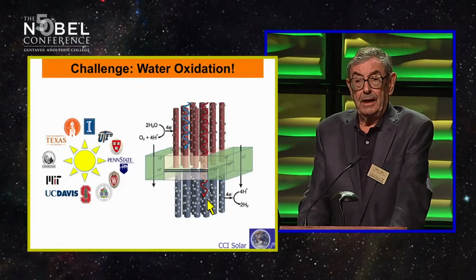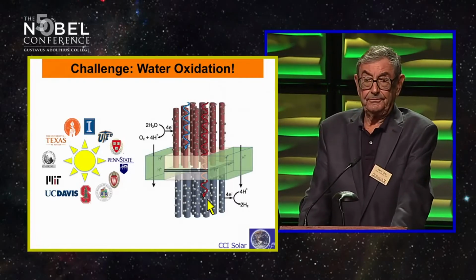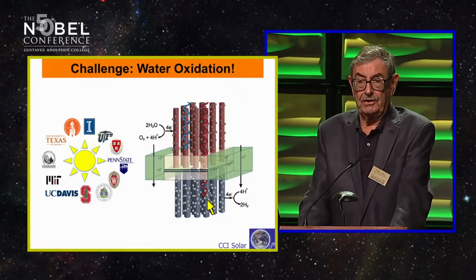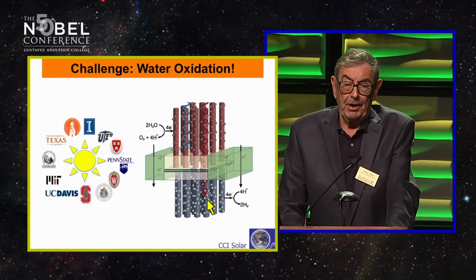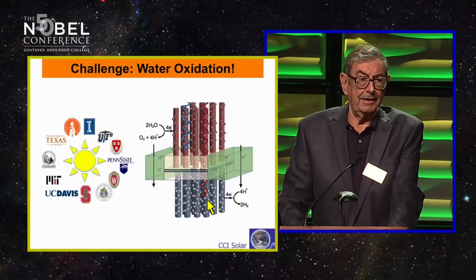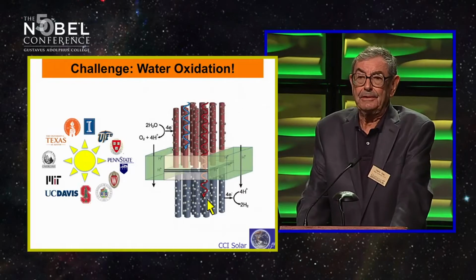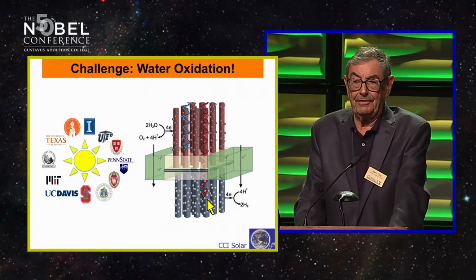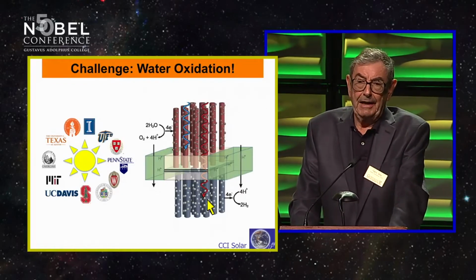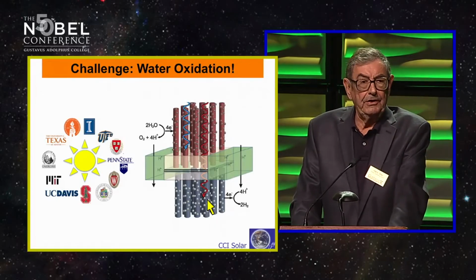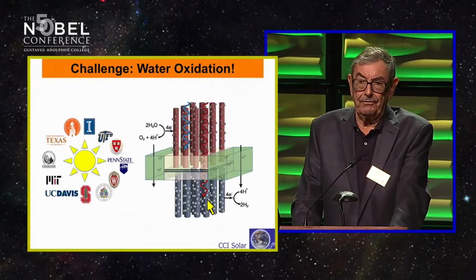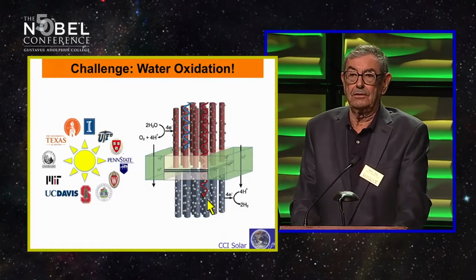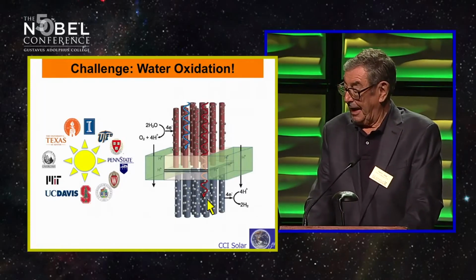So our best working photoanode is made of tungsten oxide. But the problem with plain old tungsten oxide is its band gap is too high. It's 2.5 electron volts. And we have to tune it down. The sweet spot is 1.9 electron volts, where you can absorb all the blue and green light that you need to absorb. But we figured out how to do that.